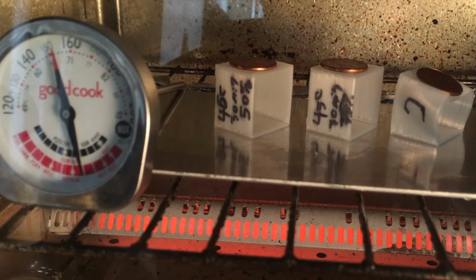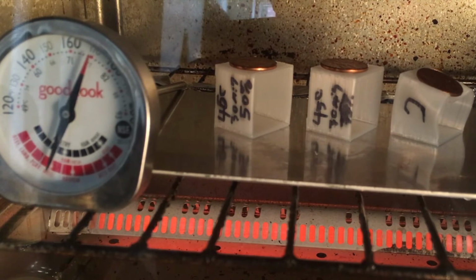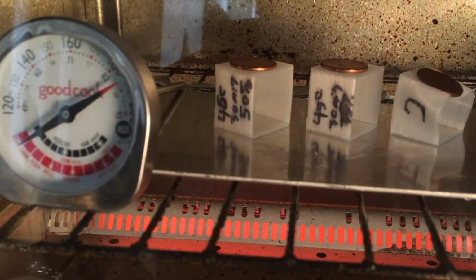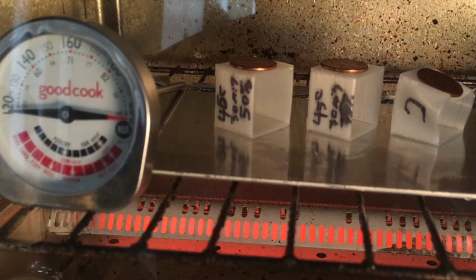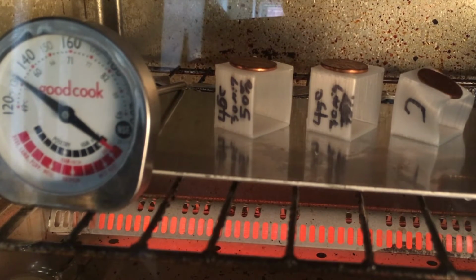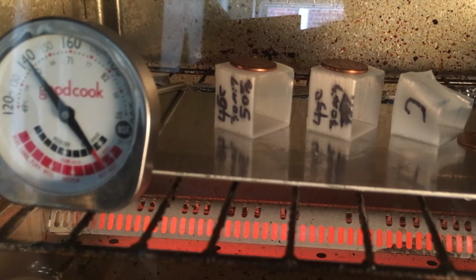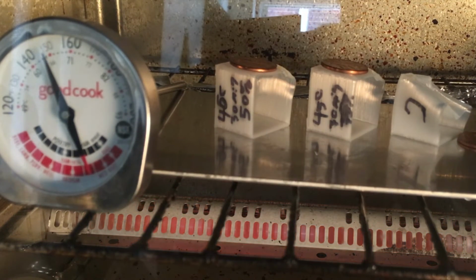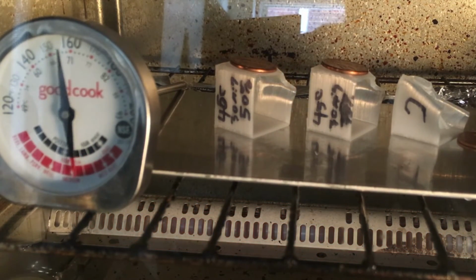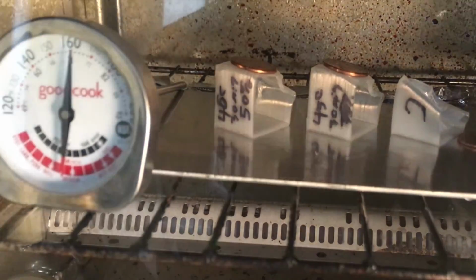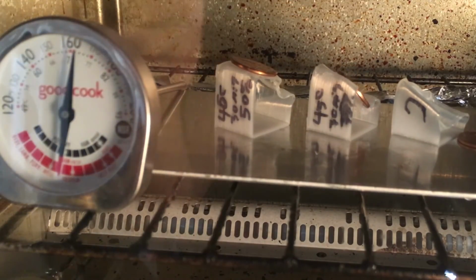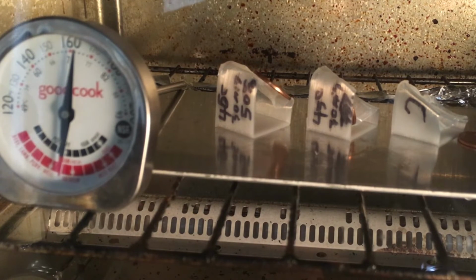Now, I set this originally to heat to 150 degrees or so, and that just wasn't doing it for the other one, so I had to just crank it up as high as it would go and then wait for them to melt. So if you look right here, they both generally start going at the same time, but it looks like the 75% starts to go first, and then that's confirmed when the 75% actually fails catastrophically before the 50%.